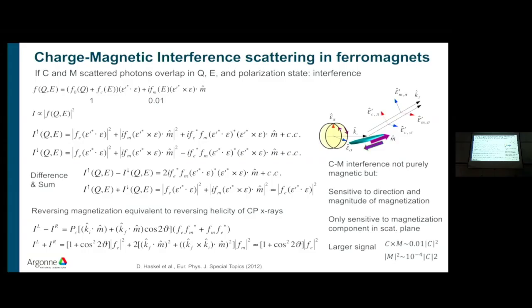And how do you change the polarization of that? Well, I can change the magnetization with a magnetic field. I put the sample in a magnet, so you apply a magnetic field on your scatterer. Or you flip it, switch the polarization of the X-ray beam and keep the magnetization fixed.